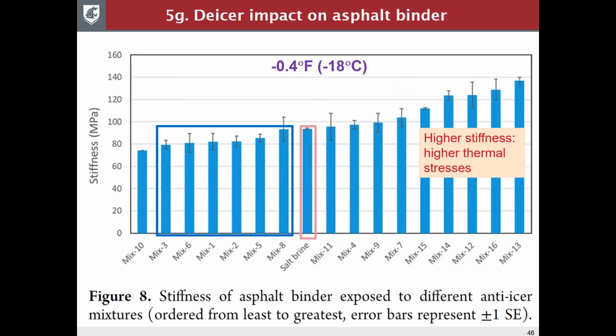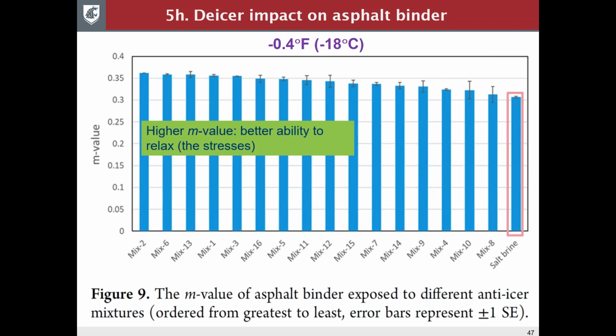And also we look at the potential risk to thermal cracking of asphalt mixture. One test is to look at the use of bending beam rheometer or BBR, which gives us 2 numbers. One is the stiffness value. The higher the stiffness value, usually the worse. It also means the higher thermal stress, which means at colder temperature that asphalt mixture tends to crack. So again, there's no statistical significance between the blue box and the pink one, but there are a number of them that actually have worse impacts on asphalt mixture. However, if we look at the left group in terms of m-value, the higher the m-value, the better ability to relax the stresses. So many of them actually, statistically speaking, have better ability to relax the stresses compared with the salt brine.